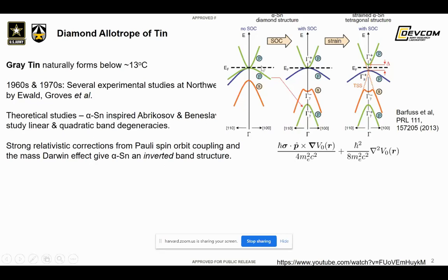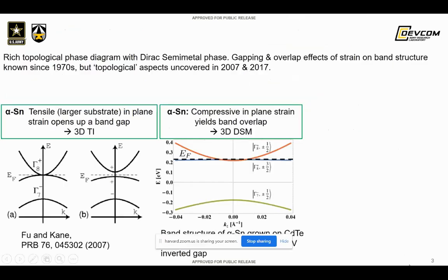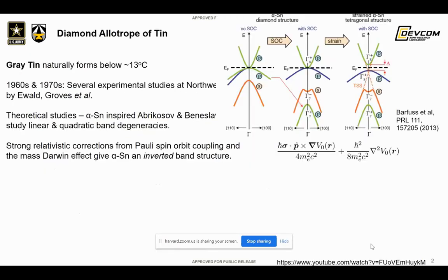So the key thing about this band structure is that alpha tin is a zero band gap semiconductor due to strong relativistic corrections and spin orbit coupling. It is quite unique in that it has a Fermi level which is pinned at the gamma 8, gamma 7 band points at the gamma point.